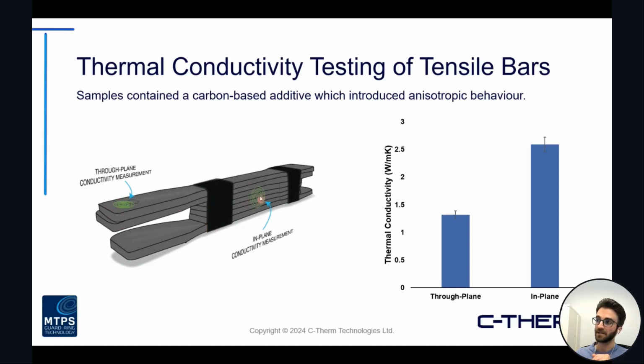But to measure the in plane here, obviously these are way too thin to cover the sensor fully. So what you can actually do is stack a few of them up, clamp them together, and rotate them to get at that type of characterization. You can see the differences in the in-plane versus through-plane measurement of these samples. The materials that were tested in this case had a carbon-based additive, which was introducing some directionality into the material itself. So just a little case example of some of the material testing setups that can be done.